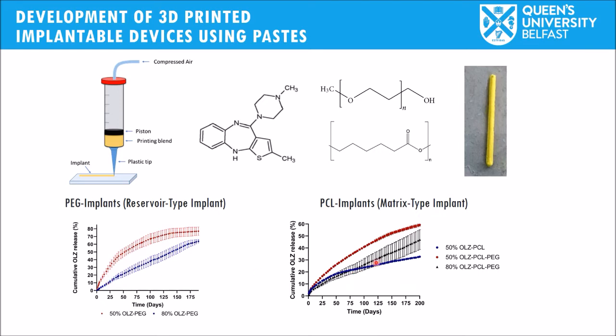Additionally, in the matrix implants we have a sustained delivery, but in this case the formulation was slightly different. The blue plot represents full polycaprolactone olanzapine mixtures containing 50% of drug, and the red one shows a higher drug release. In order to achieve a higher drug release, low molecular weight polyethylene glycol was included in the formulation, so obviously it's going to generate a more porous structure during the procedure because of the hydrophilic nature of PEG, and it's going to translate into a higher drug release.